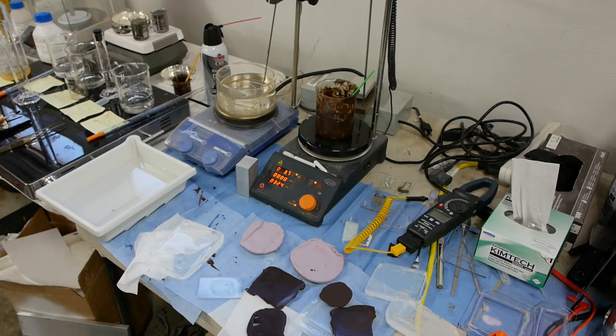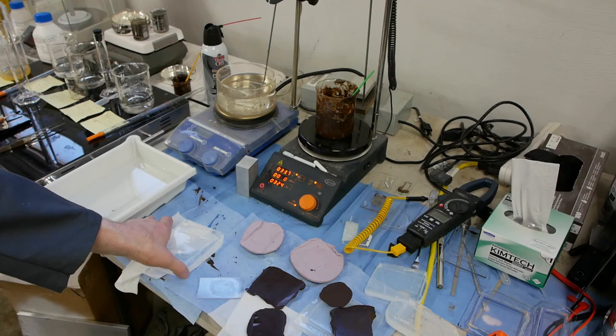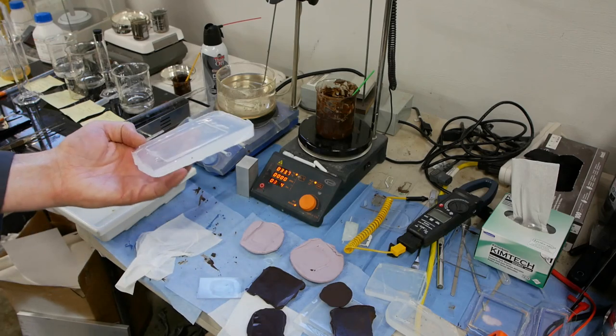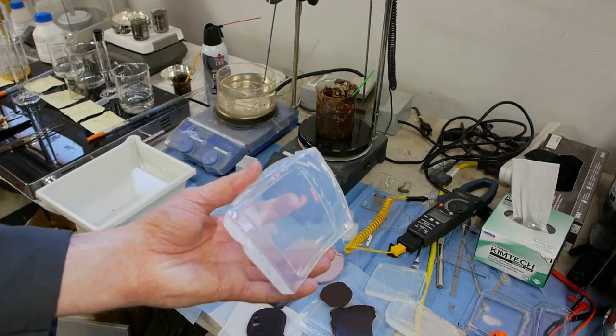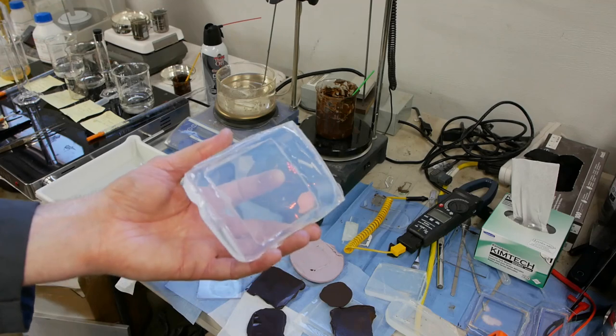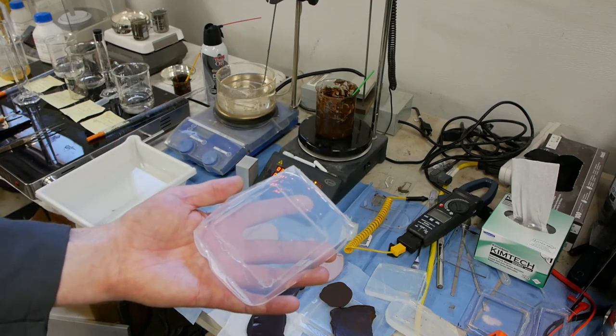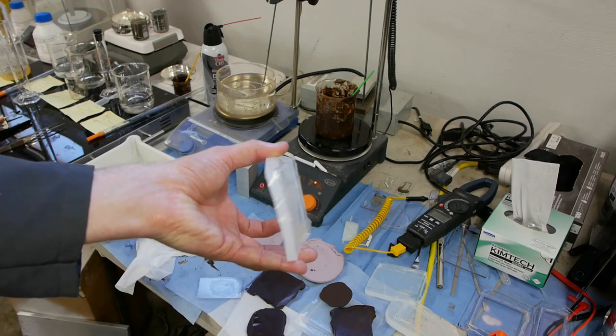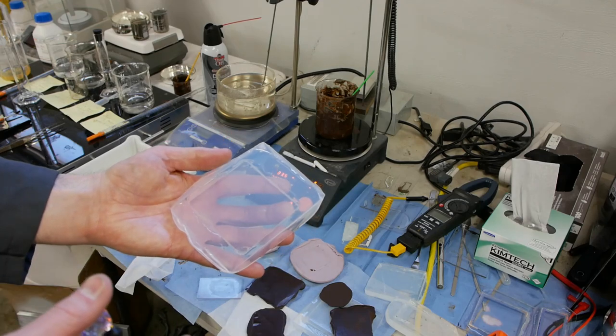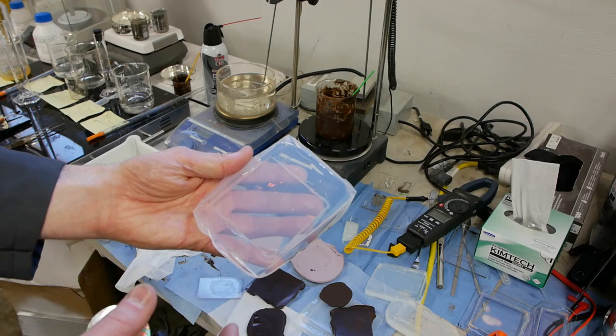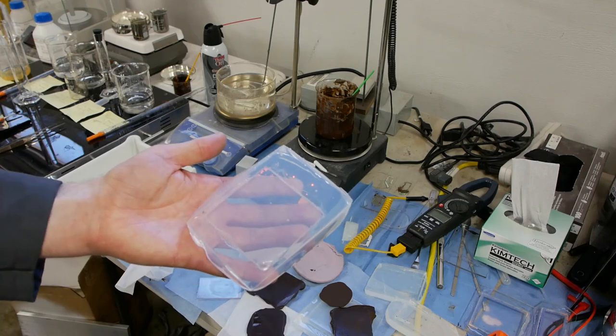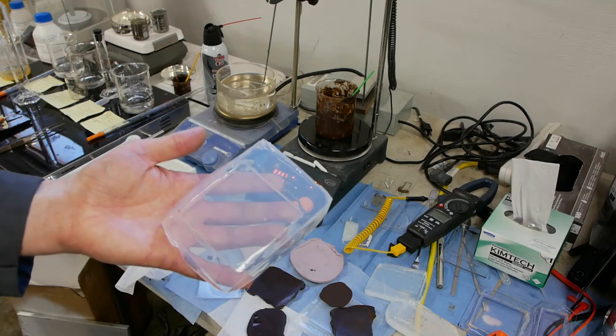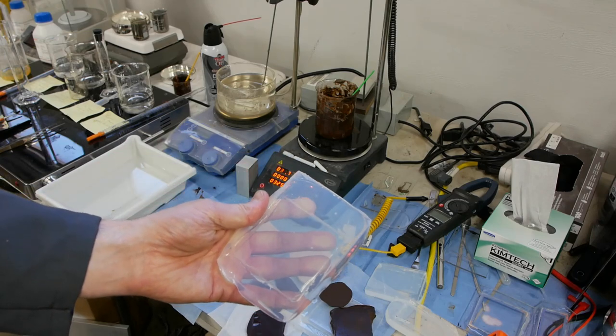So the solution that I came up with that ended up working really well is to make a silicone mold of the taken apart hologram and then pour the chocolate into the silicone mold. So this is great because the silicone is pretty compliant. So as the chocolate cools, it contracts a teeny bit and the silicone just goes along with it. Whereas the plastic would not, and then the hologram would rip itself apart because there was no compliance.